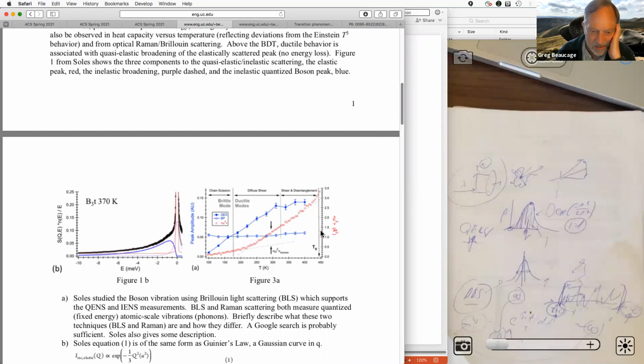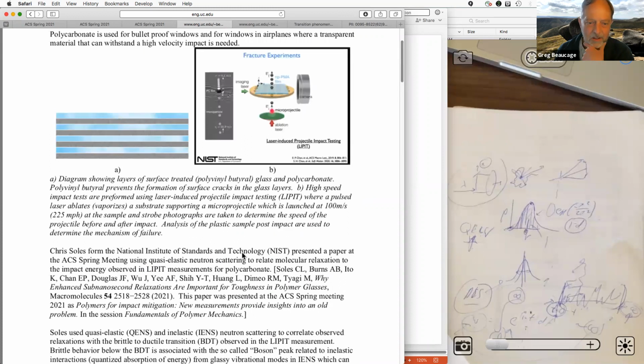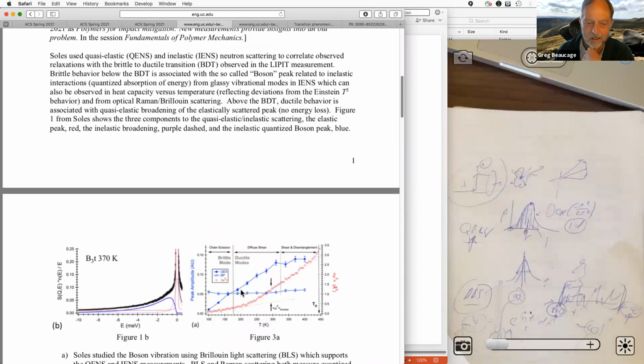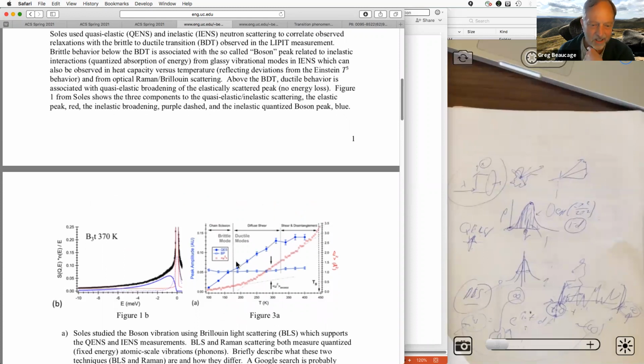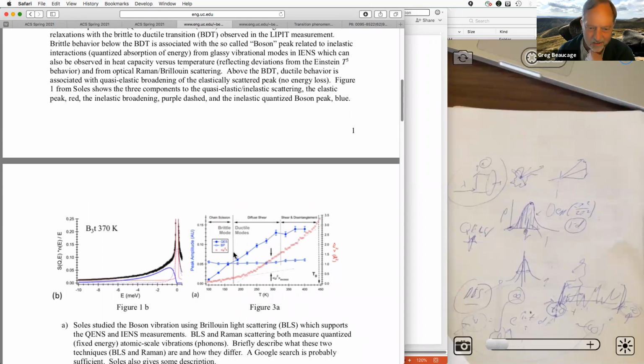And they see a strong signature, right, between these boson or phonon vibrations due to the inelastic, and then this quasi-elastic, which has to do with motion of the molecules. So this business of chain scission versus shear and disentanglement of the chains is the answer to this brittle to ductile transition in polycarbonate. And then the important thing is that they get ductile under the speeds they're interested in this LIPIT measurement. So that's why polycarbonate is better than polystyrene. It doesn't have that signature. At some point, not in this paper, but Souls compares different polymers and shows that basically polycarbonate has a special feature here, that this brittle to ductile transition happens.